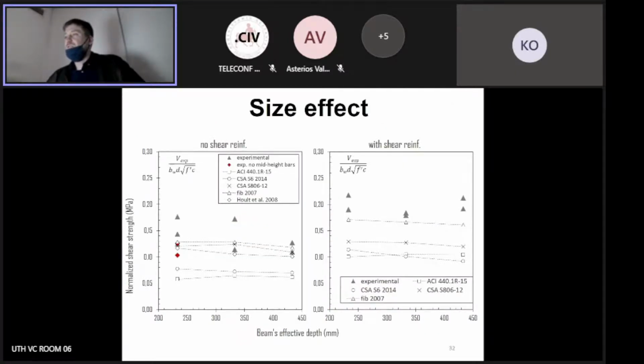Here are some results from a size effect. The experimental results from the beams are gray. Here we have no shear reinforcement. Here we have shear reinforcement. If you look at this, you can see that there is a kind of size effect for small beams, which were the smallest were around 240 millimeters, tallest were around 460. You see that it decreases if you take, of course, the average of all these tests. They were the same tests. You can kind of see this decreasing trend. If you provide shear reinforcement, according to the literature too, you should not see size effect because it's effectively mitigated. And I saw that too.